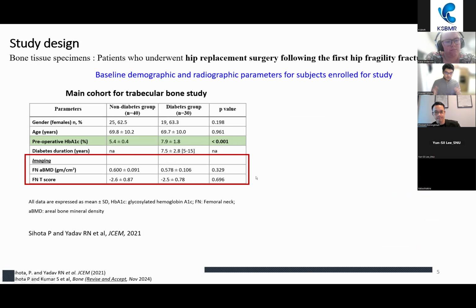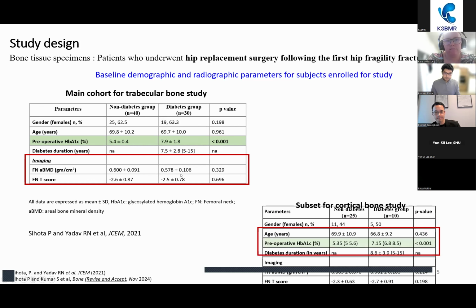So I want to come to the study that I have conducted. For that, we collected patients who underwent hip replacement surgery following a first hip fragility fracture, with and without type 2 diabetes. Our main cohort includes 40 in the non-diabetes group and 30 in the diabetes group. In baseline demographics, all is comparable except HbA1c, which is significantly higher. DEXA parameters are also comparable between the groups.